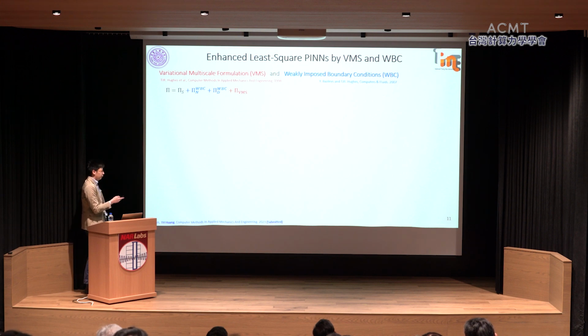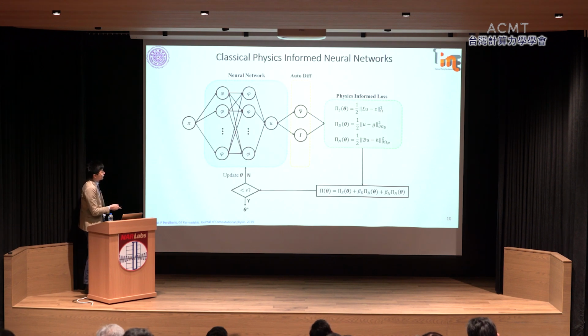But you will find the problem is that the penalty parameter will be tricky in the advection diffusion problem, because if you choose a large penalty parameter, you get an ill-conditioned system. If you choose too low, you cannot impose it. And also, we found out that the inflow and outflow boundary conditions actually need different regularization. That will become an issue in modeling.